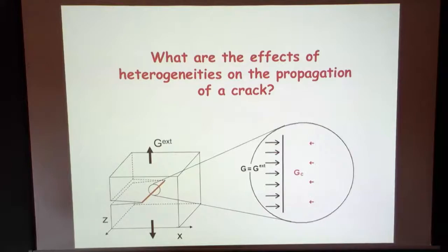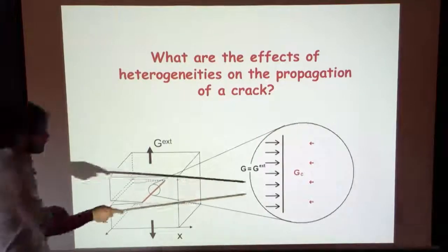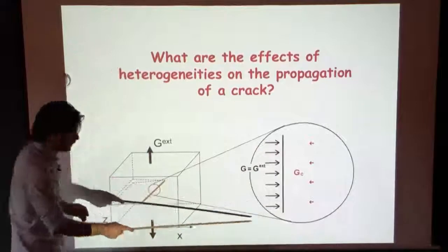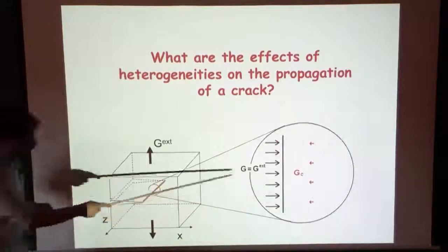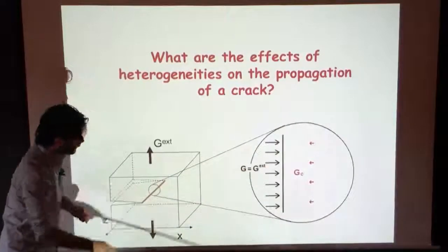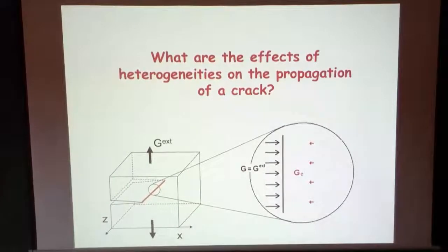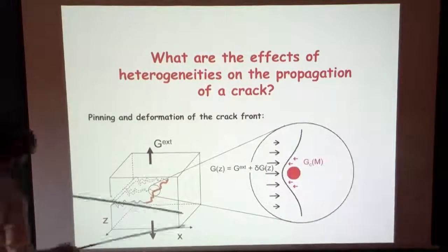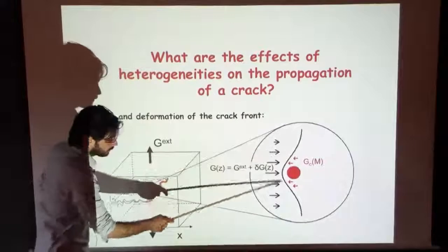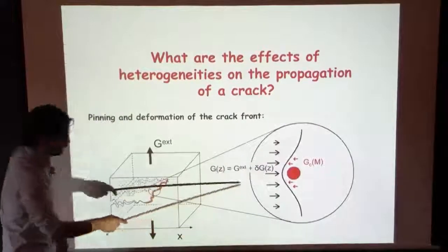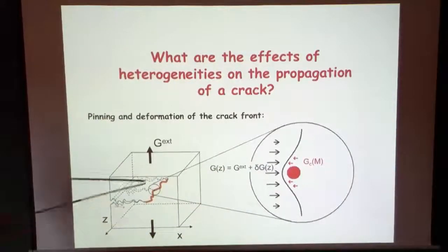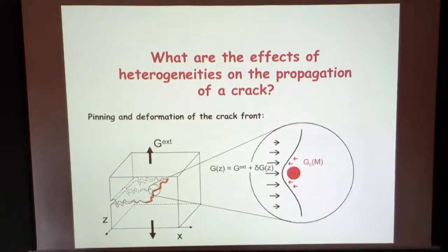So I'm going to consider heterogeneity only in fracture energy and focus on that. In a medium where I have a homogeneous fracture energy, the crack is straight, and the driving force is constant along the crack. And as soon as I introduce some heterogeneity, I'm going to deform the crack front, and I'm going to have a driving force that might depend on the front position.